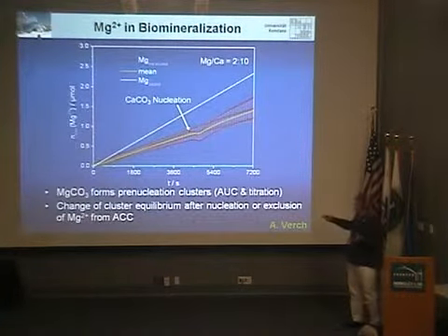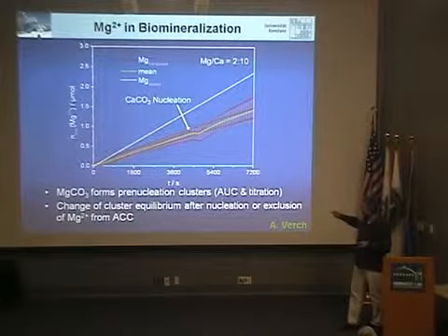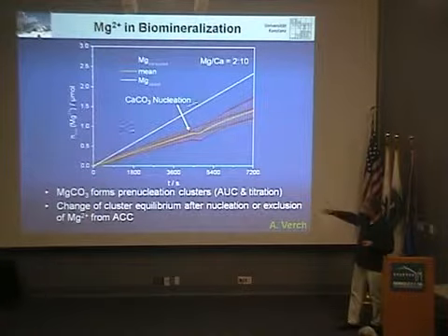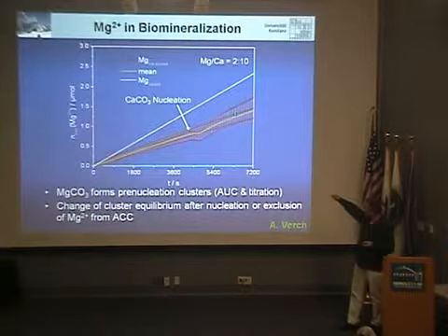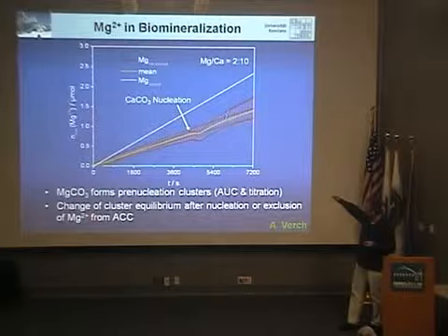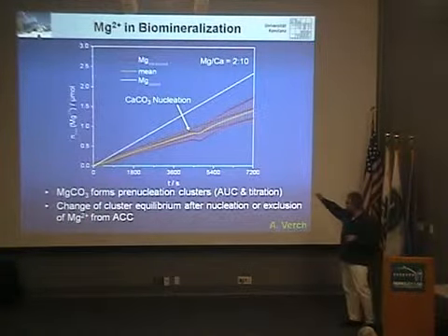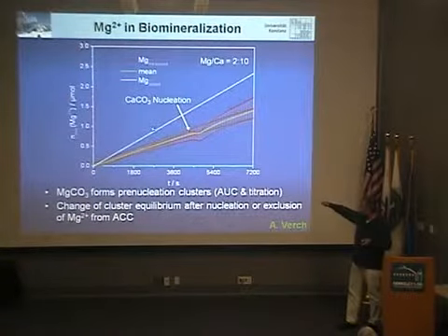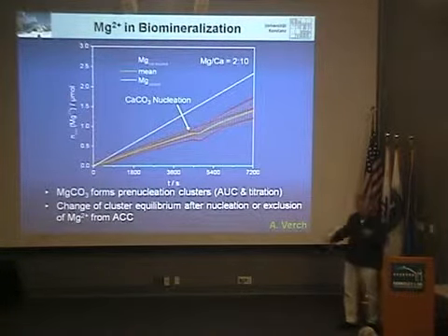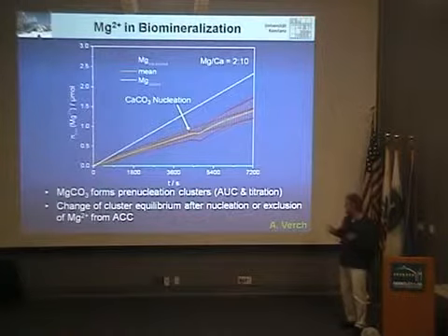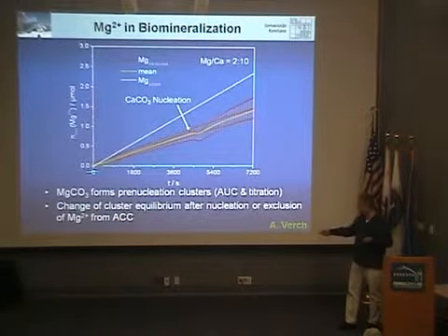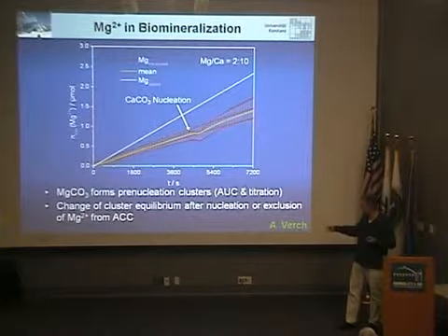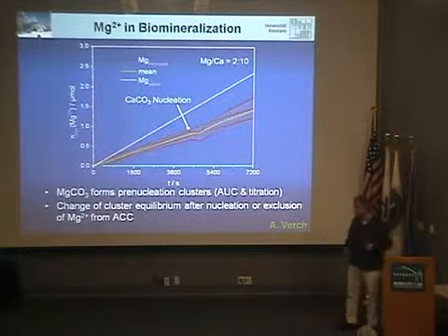And the curves you get are similar to what you know from calcium carbonate. So now we detect the free magnesium. This is the magnesium added, the white curve. And here you got some variation in the detected magnesium. So these are 3 or 4 red experimental traces, which are averaged as the yellow curve with the error intervals. But you see, again, you get a difference between added and detected magnesium carbonate. And it also forms, that is a message, magnesium carbonate also forms prenucleation clusters. We detected them by analytical ultracentrifugation separately.